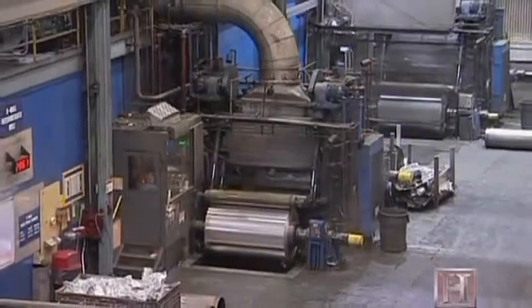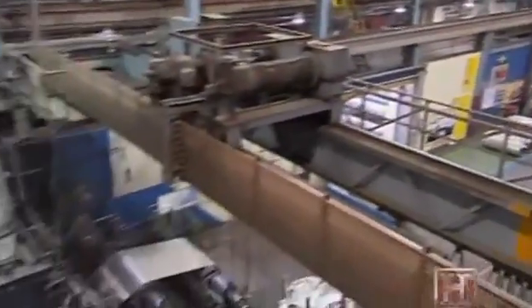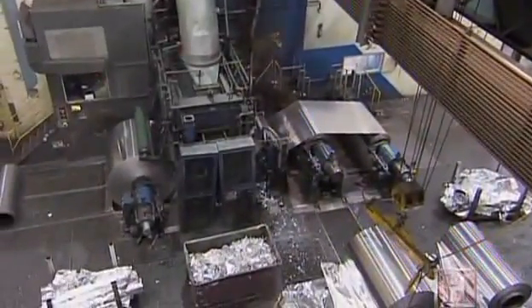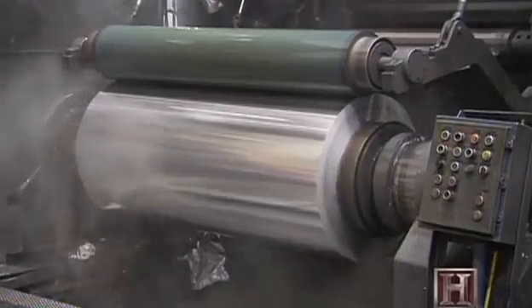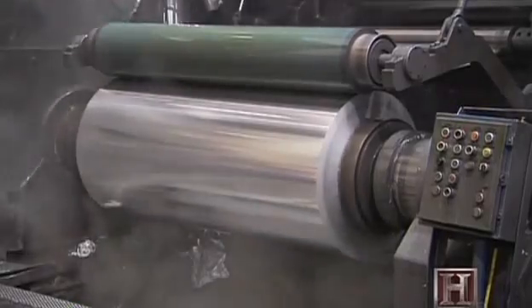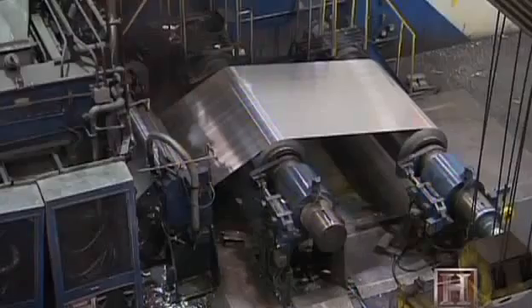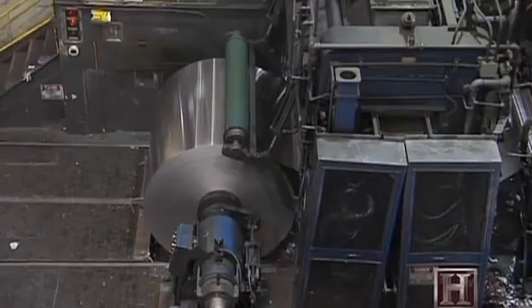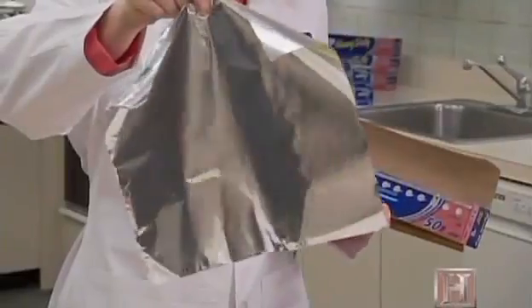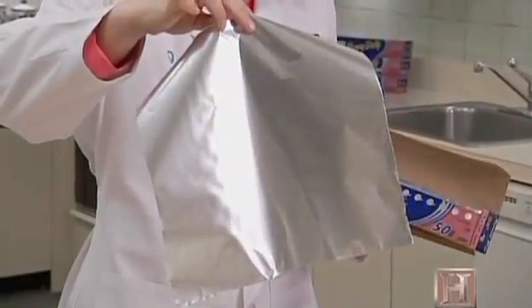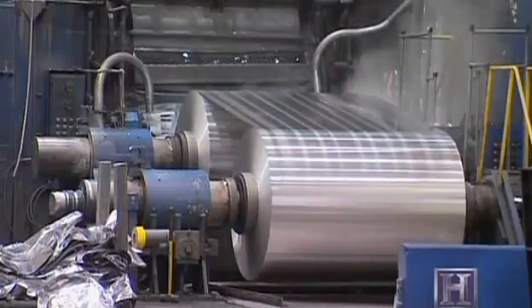It's also getting a lot longer, as the 3,000-yard long coiled sheet makes 6 passes through 3 different rolling mills. When it finishes on our finishing mill, it's about 240 miles long because we've reduced it and increased the length. This final pass through the finishing mill holds the secret to why aluminum foil is shiny on one side, but not the other. So in order to support the metal and ensure we can pull it through the mill, we double pass it. We have 2 sheets of metal running through the mill at the same time.